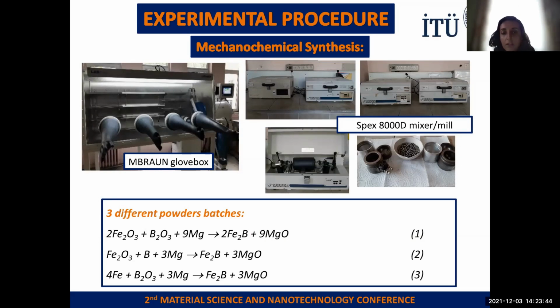For this study, we use SPEX type high energy ball mills. As you can see from the photos, there are four SPEX high energy ball mills, and we can also see the inside of this high energy ball mill device. The mechanochemical synthesis was conducted in stainless steel milling vials using stainless steel milling balls.